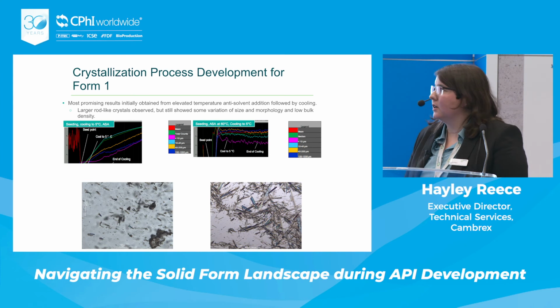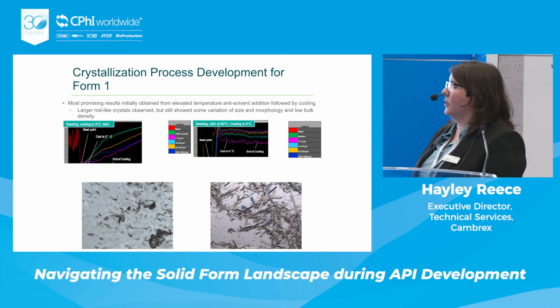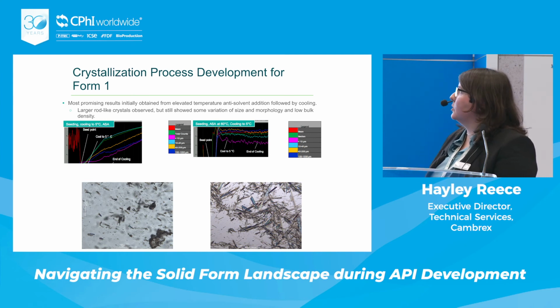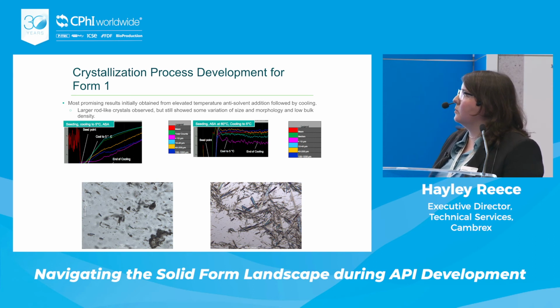So over the next few slides, we'll go through some of the data that is generated from these crystallization development work programs. We do carry out a number of experiments, at least 8 to 10 crystallizations on the larger scale, and we'll go through the results of 3 of these crystallizations. The first crystallization was basically seeded, and then we cooled down to 5 degrees before adding anti-solvent.